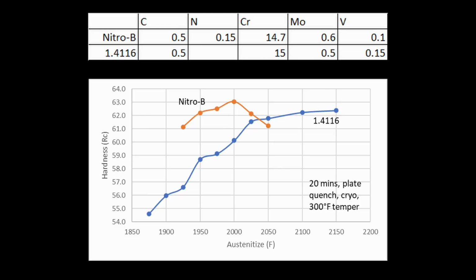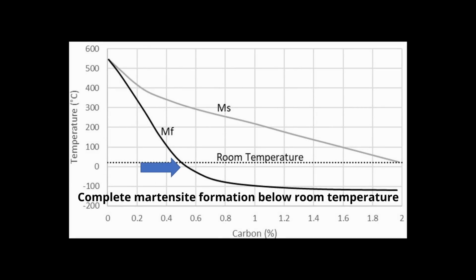When we heat up the steel hot, it's called that austenitizing temperature because we form a steel phase called austenite. When we quench rapidly, it transforms to a phase called martensite. Retained austenite is when that high temperature phase austenite is not transforming to martensite. And so if we get too much carbon nitrogen alloy in solution, that austenite is too stable and it doesn't want to transform to martensite. And using cryo will transform more of that austenite. But in this case, I used cryo and we still reached a point where we couldn't transform all of the austenite to martensite.